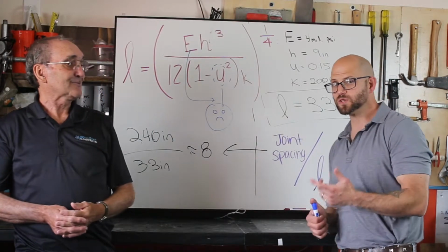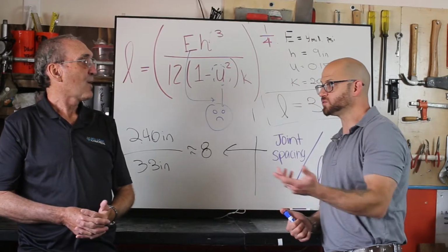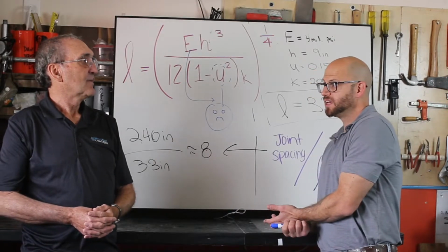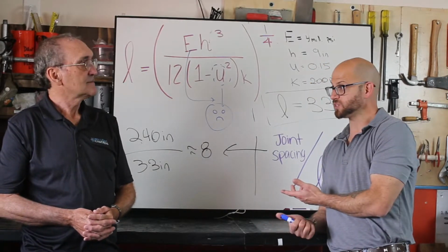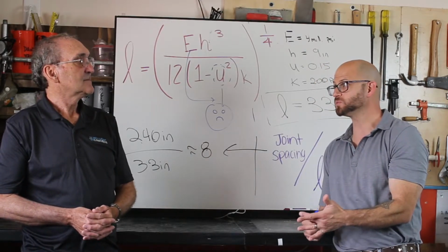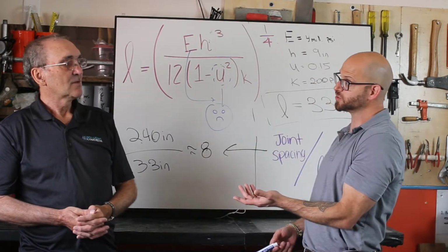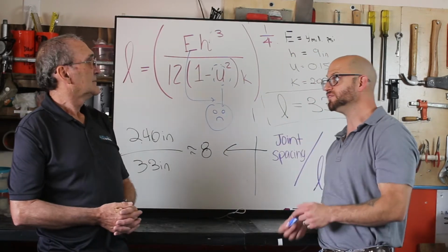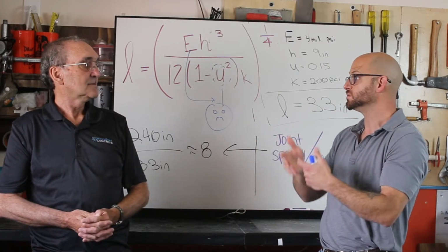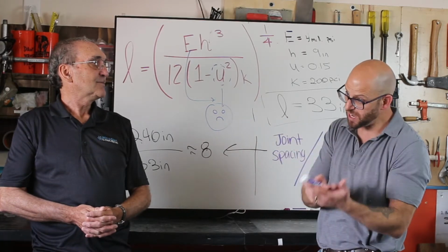The reason we want to use real values for real projects is that it's going to cost money to find those values out. A 28, 56, and 90-day modulus of elasticity test is not inexpensive, but if you're doing this type of project where you have to be concerned about it, it shouldn't be that big a deal. Some of the newer materials that we're using, carbon nanotubes, steel fibers, and newer things of older technologies help us enhance concrete and change these values significantly. What if you can spread out your spacing to 20, 25, 30 feet? That saves time and money.